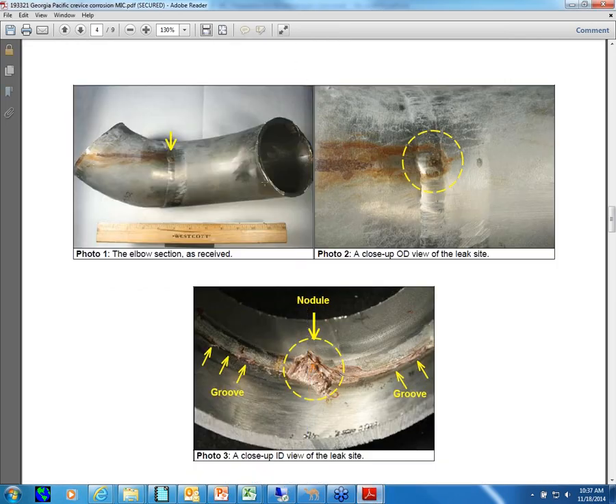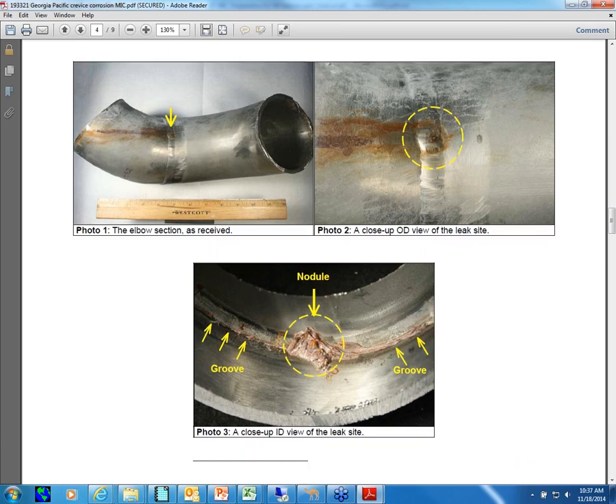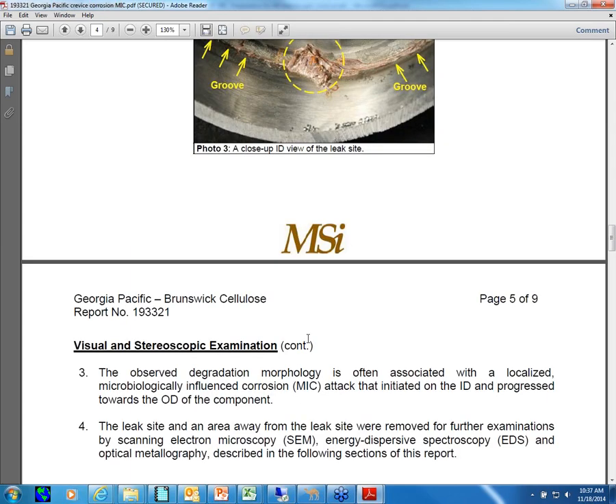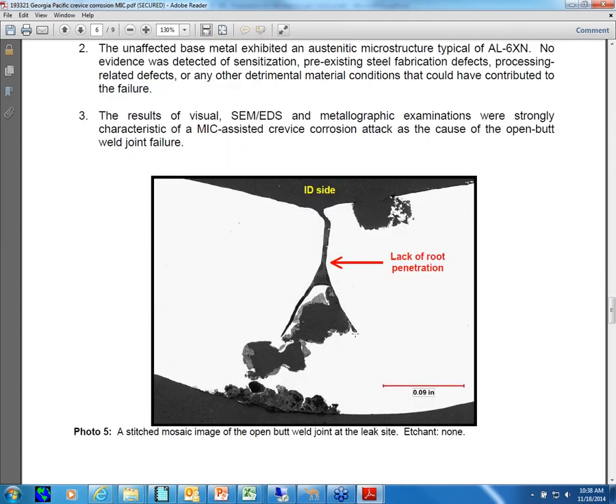I've got one more analysis to show. This one is the AL6XN, the 6-moly super austenitic stainless steel. This would be where we see a leak in a pipe and wonder what's going on. We send it out for metallurgical analysis, and they could actually see the nodule. But what they found was a poor weld, a lack of root penetration welding. So these guys came back and told us, hey, your problem isn't MIC and your problem isn't chlorides. Your problem is you had poor welding.